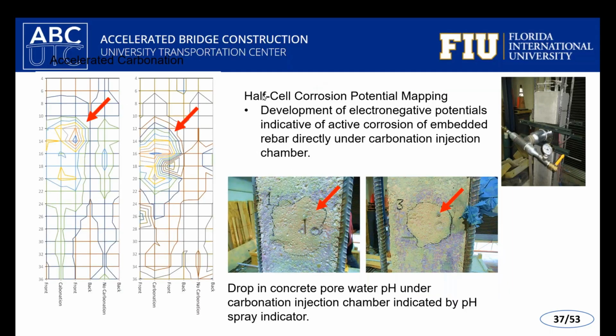So the top right-hand picture shows that very method that we developed here at FIU. We had a pressure vessel, just some flanges and some connecting pipe components connected to the CO2 tank. We pressurized different vessels, fitted onto the surface of the concrete directly above where those corrosion sensors are located. And we measure half-cell potentials, and we also use our phenolphthalein spray. So I'll talk a little bit more about those colorful pictures we have in the bottom.